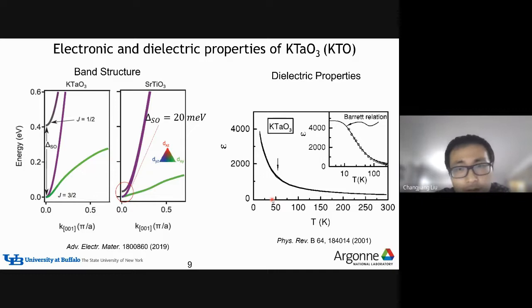So as I mentioned just now, the potassium tantalum oxide is in many ways a cousin of strontium titanium oxide. So for example, here I'm showing you the electronic structure. In both of these cases, the electronic band structure is derived from the t2g manifold. Basically, it is the mix of dxy, dyz, and dxz orbitals. So the one difference between potassium tantalum oxide and strontium titanium oxide is that in KTO, the spin-orbit coupling is quite large. In fact, it is more than 1 order of magnitude higher than that in STO. And because of this spin-orbit coupling, the t2g manifold is split.